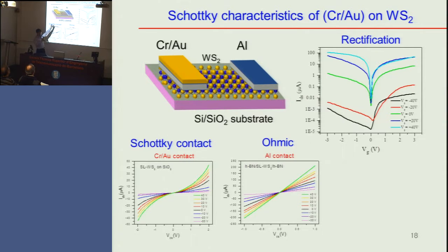So one side is a Schottky barrier, the other side is ohmic. So I can use this device as a test device for the experiment. I saw rectification without any p-n junction between 2D materials. So I can conclude that all the reports might just be reporting the behavior of Schottky barriers as a rectification effect.